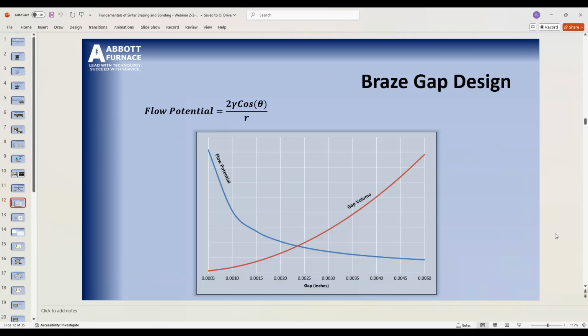Okay, so now let's talk about gap. We want a really dry atmosphere, just like we would for our sintering process. But what gap do we want? Well, look at capillary action: when you put a straw in a glass of water, the water crawls up the straw. If you put a big straw in, it doesn't crawl up as high as a little straw, because you have to lift more weight using the surface tension. Well, that's what we're looking at.